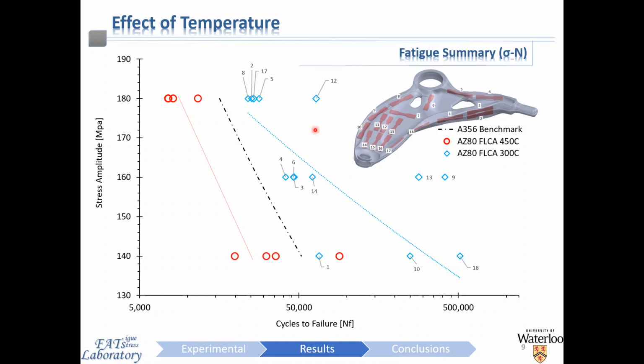So now overlaying all these individual data points that we've collected over the SN curve, one can easily appreciate that even at the component level of forging, a large amount of variability occurs in the properties, which is highly a function of the location within the forging itself. So indicated by all these numbers are all the different forging locations within this component.